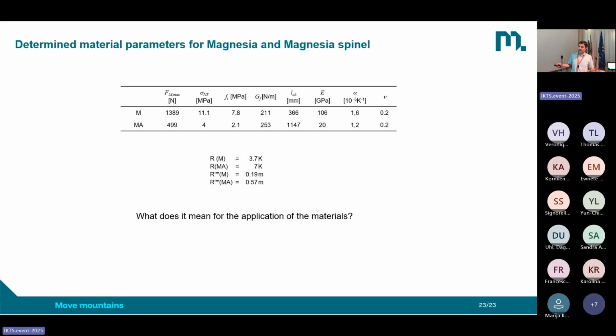What do we learn now for refractories? If you do not have the chance to increase the strength so far that you can avoid crack initiation, then it's better to have a lot of resistance against the crack propagation. And this is what the industry is doing. And I hope I could increase your understanding why this is the case, and why high strength is not in any case an advantage. Thank you.